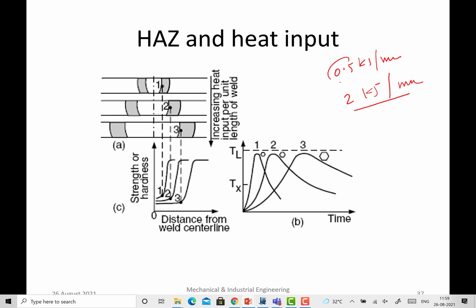When you apply less heat, what you are getting is a very small nugget size and a very narrow heat affected zone. When heat is increased, nugget size increases and your HAZ size also increases. So these will keep on increasing. The widths will keep on increasing. Okay, and that is what you can see here. The minimum hardness zones are also increasing. The width of the minimum hardness zones are also increasing.